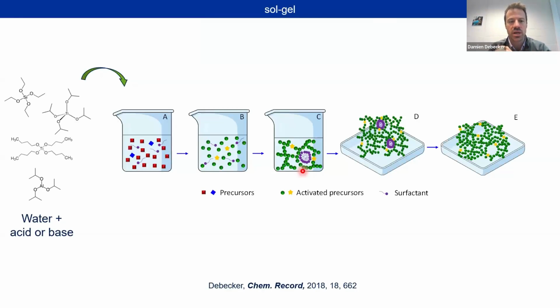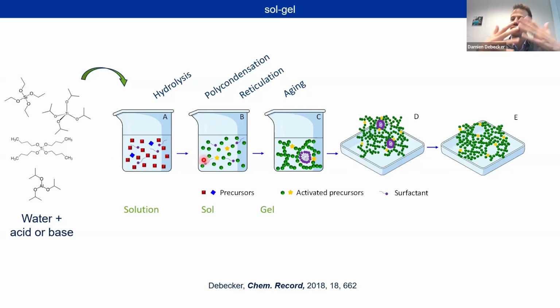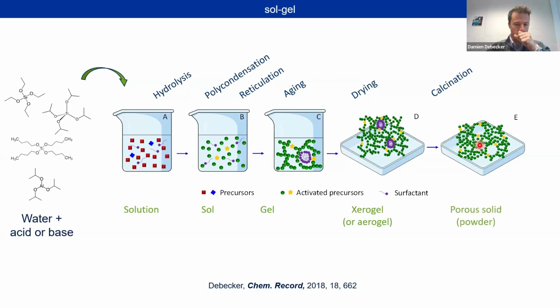For this, I first need to take a step back. Maybe you're familiar with sol gel chemistry. In sol gel chemistry, what we're going to do is to start with molecular precursors, typically alkoxides, that you would put in water and activate by hydrolysis. You have then reactive precursors that will start to react through polycondensation reaction to reticulate to form a gel. And this gel is going to be aged and dried and then calcined to get a porous material. There are two main challenges.